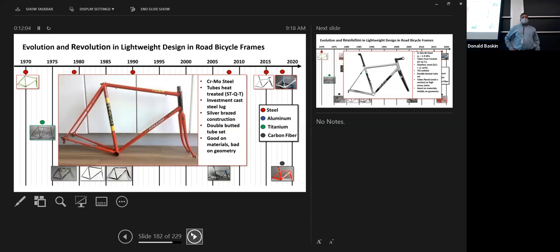So this frame here is an interesting example. This is a chrome moly, but it's heat treated. So the tubes are heat treated. In order to avoid changing the heat treat on the material, you have to braze it at a very, very low temperature. You don't want to get the metal too hot and grow the grains or overheat the precipitates. So in this case, they use silver solder. You get a little artisan who's very skilled with the acetylene torch, and they heat this thing up just a tiny little bit. There's a little bit of brass, and the joint and the lug fit so tightly together that capillary action just sucks in the molten silver, and you get a nice strong joint.